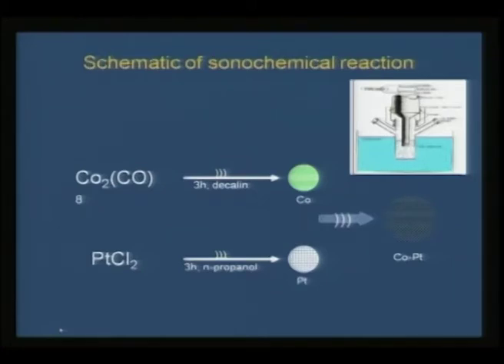For example, one of the most important alloys is cobalt platinum alloys, which is also used in memory storage devices. So you can take Co2(CO)8, which is nothing but cobalt carbonyl, and if you sonicate this for 3 hours in decalin solution, you will get cobalt nanoparticles. Similarly, in the case of platinum, you can use platinum chloride, and if you sonicate for 3 hours in N-propanol, you get platinum nanoparticles. So if you are looking for cobalt platinum nanoparticles, take these two together and sonicate for 3 hours, and you can get cobalt platinum nanoparticles.